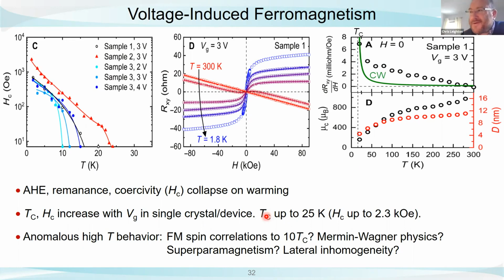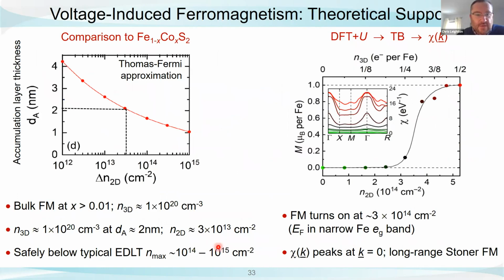No, it's a great question, right? And this is sort of the most interesting part of this, and it's what we're working on right now. So let me go through the two possibilities. One of them is, in my mind at least, Mermin-Wagner type ideas, right? Because we know how deep this layer is being accumulated. I can show you the calculations on the next slide. We think that we have about a 2 nanometer accumulation depth. So 90% of the carriers are only 4 unit cells from the surface. So it really is confined to the surface. We're in a 2-dimensional limit very much.